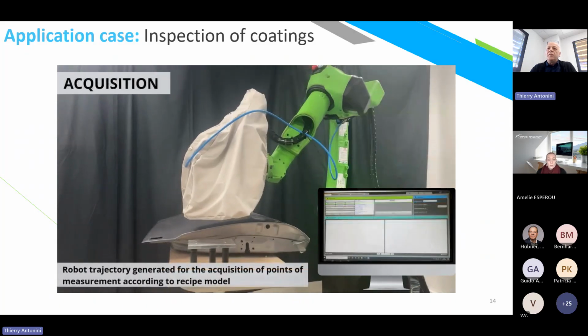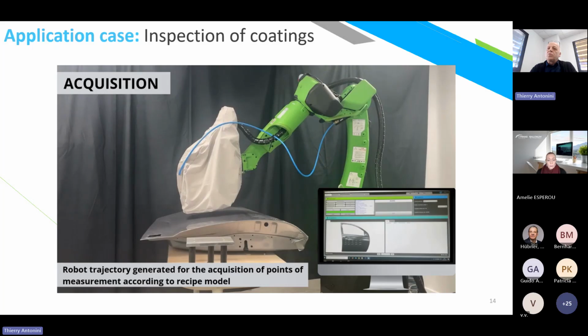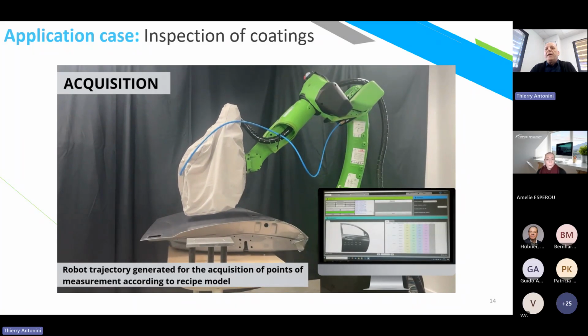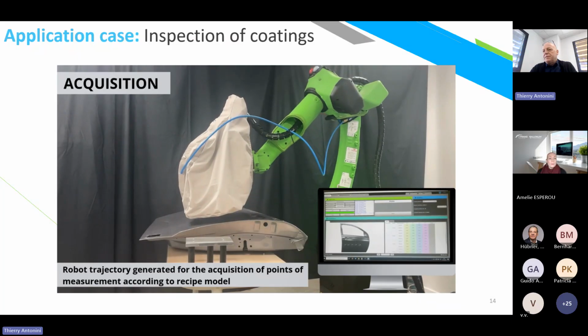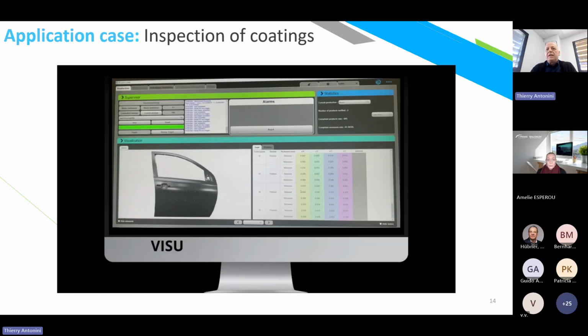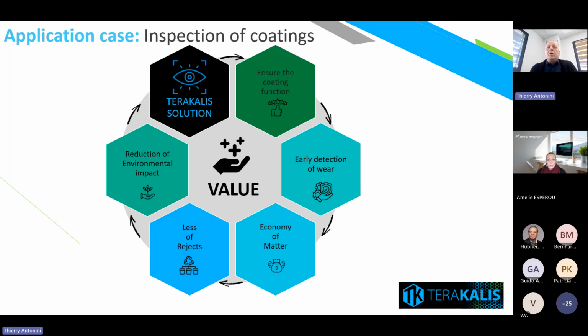The system will start to move and follow the surface of the part in order to do measurements on the fly, I mean in real time, based on trajectories that can be defined and series of points which have to be located beforehand, in order to ease the table of measurements which are consolidated afterwards. There is a lot of value behind such an application. It could be quality improvement, but also productivity improvement by reducing materials, by early detection, or by limiting rejected parts due to bad quality, by anticipating and locating defects, gaining more knowledge on the process itself, and also reducing some environmental impact.